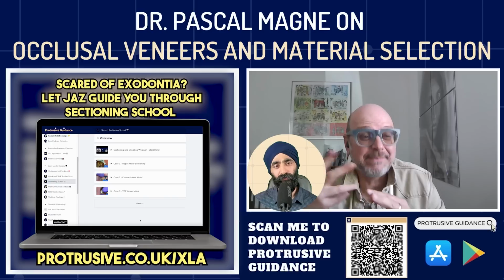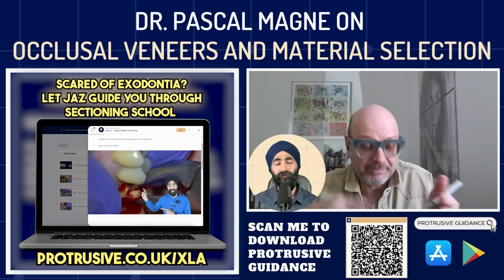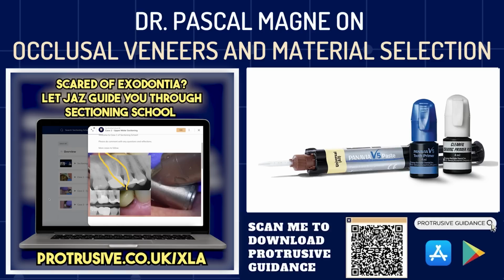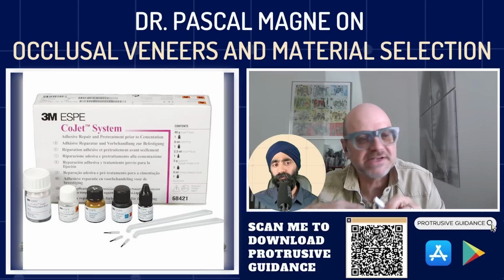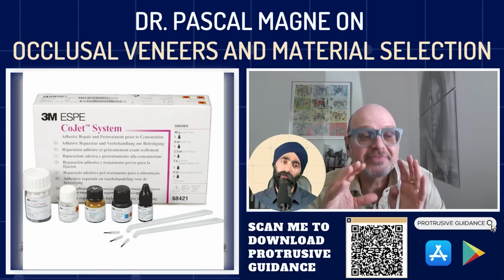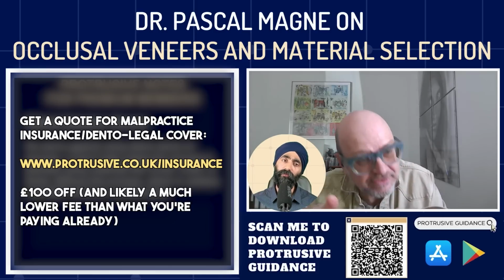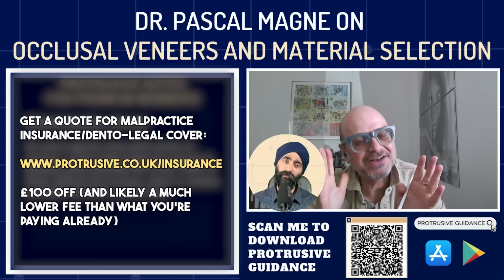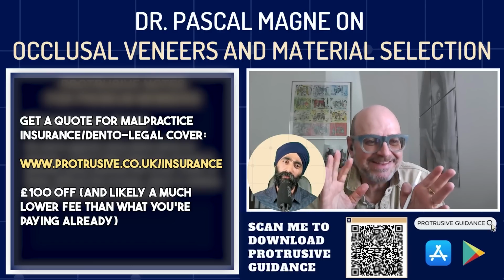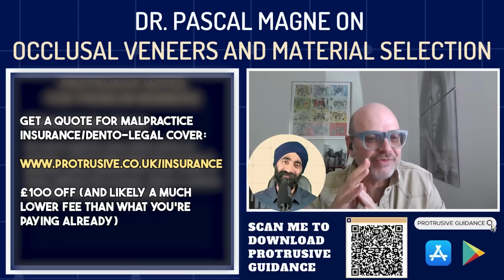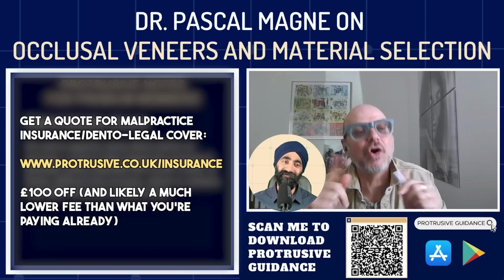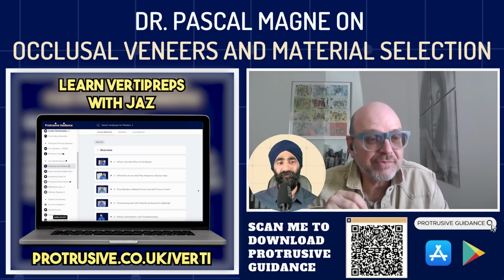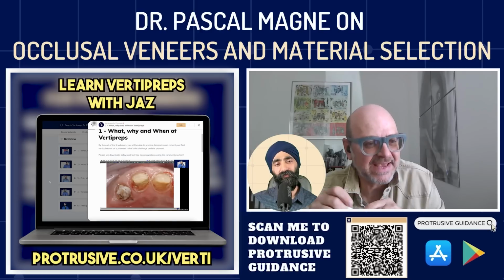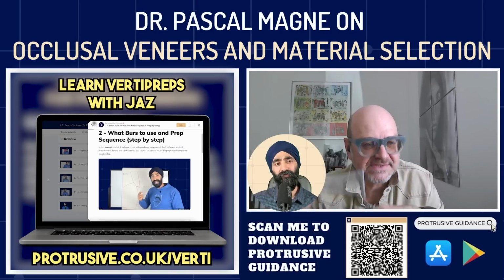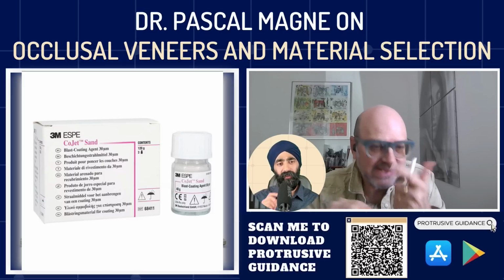And so you have to use cements that have MDP like Panavia or specific zirconia primers. You could also use CoJet, or CoSil or Siljet from Danville, and you could silicoat the zirconia and then use a silane, right? I just want to tell your audience here, don't use silane on zirconia. It will not help. It will not do anything unless you silicoat the zirconia by air abrading it with a silicated sand like CoJet, CoSil, Siljet, etc. If you are not doing that, the silane is useless.